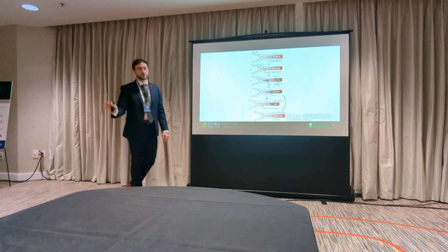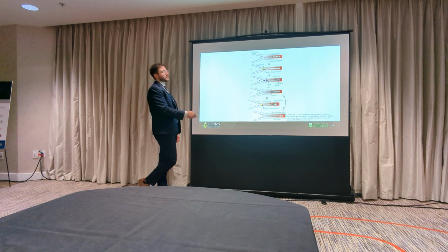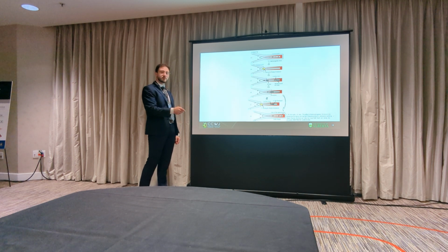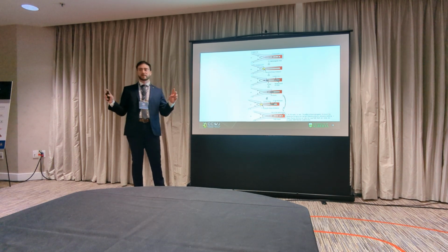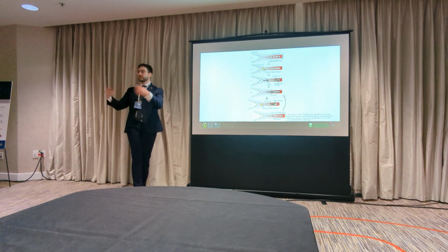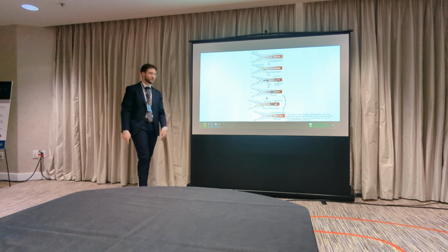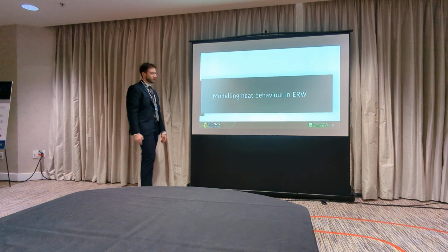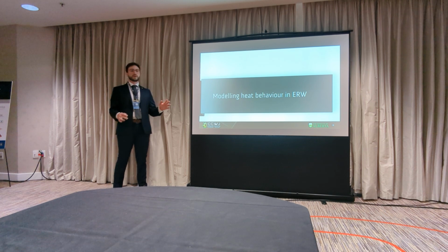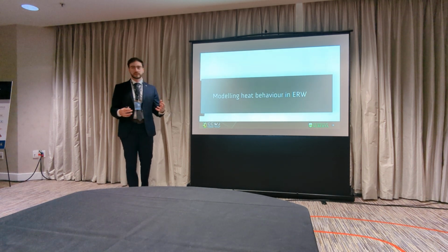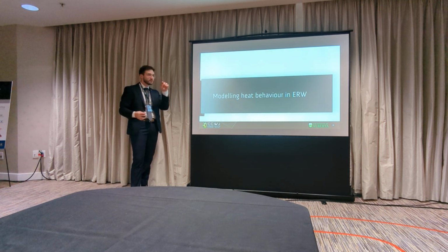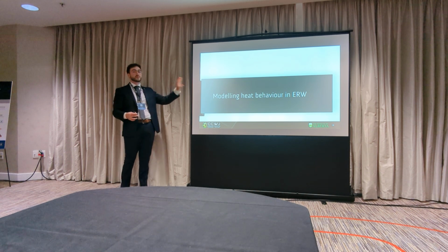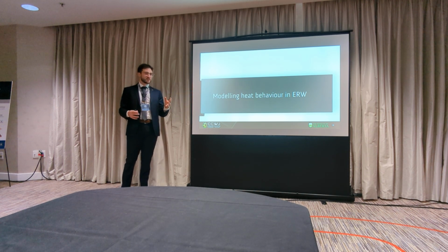And this is the theory: if you have another flash event that occurs before that bridge completes its full sweep of the V, then now you have another short circuit here, and this bridge is retained. And this bridge essentially sucked back oxidized molten metal, which is what the penetrators are essentially. So those are the thoughts about how an unstable weld zone can lead to penetrators. That last concept was presented in 2009. Nobody has studied it since then.